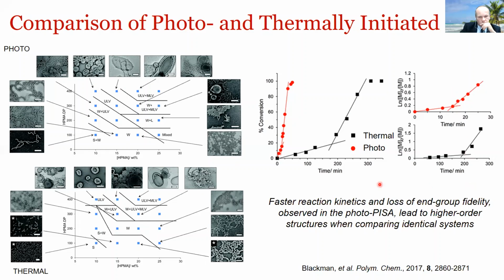And the result of that is, if you look at just the two phase diagrams, this is the photo and the thermal, hopefully you can see quite quickly that the photo initiated PISA leads to higher order structures when compared to thermal. But you also see quite a significant loss of end groups. And this is one of the first PISA bits of work we did in the group, and it was really started by Lewis Blackman, who is a PhD student who's now at CSIRO.